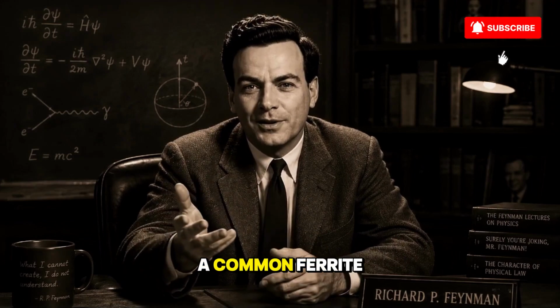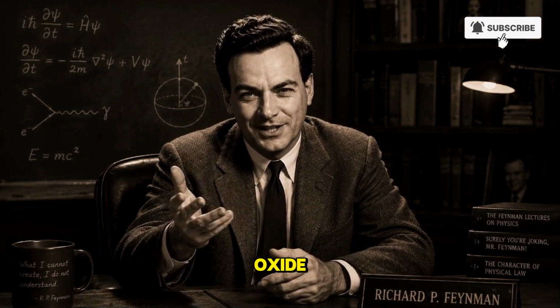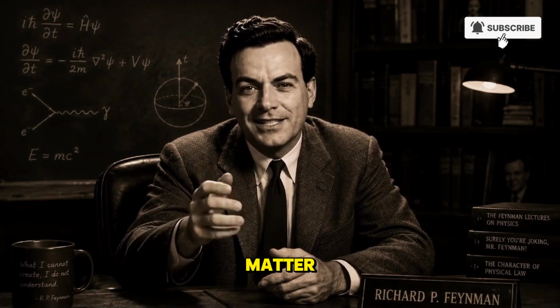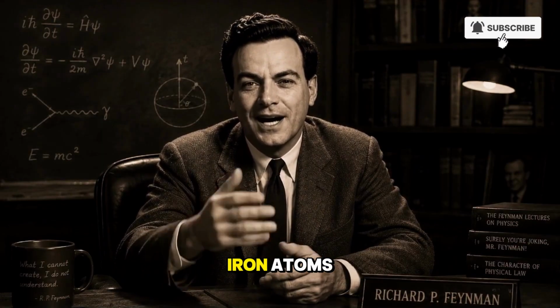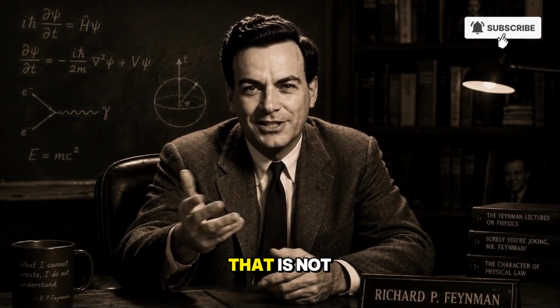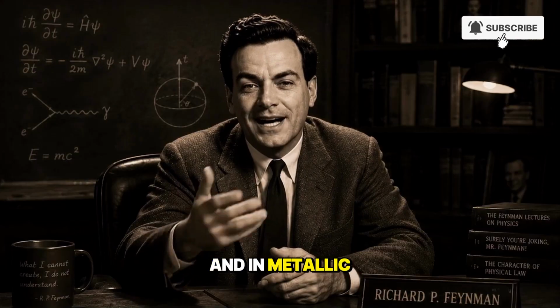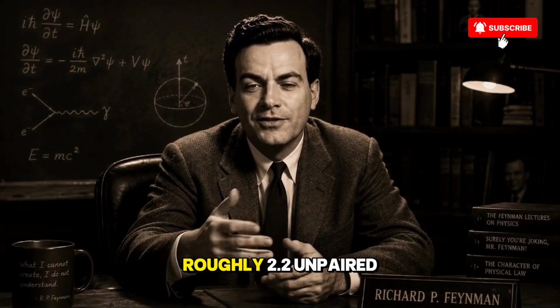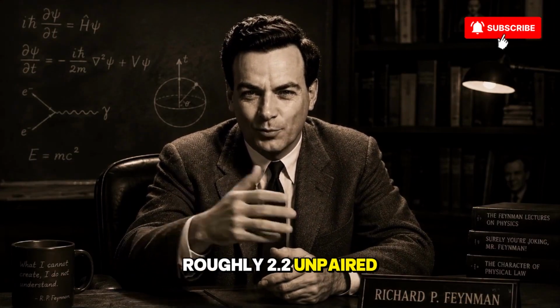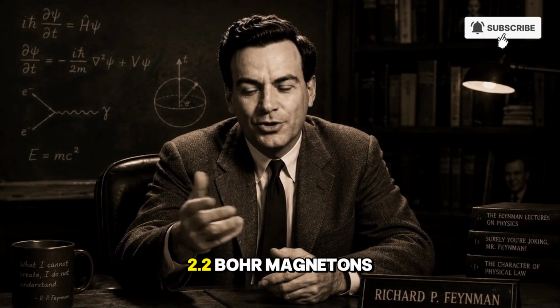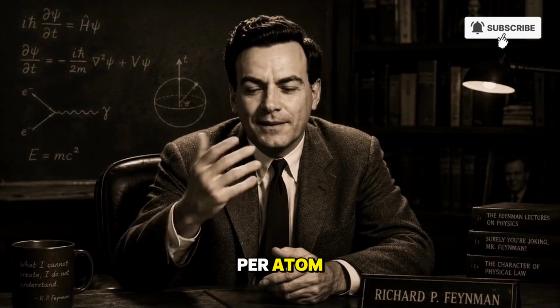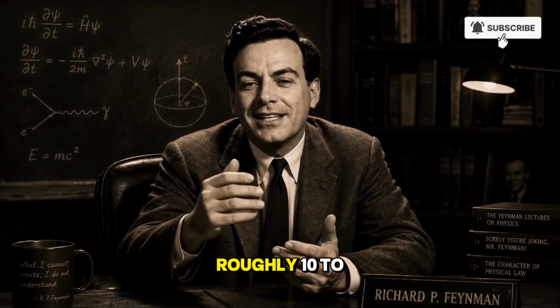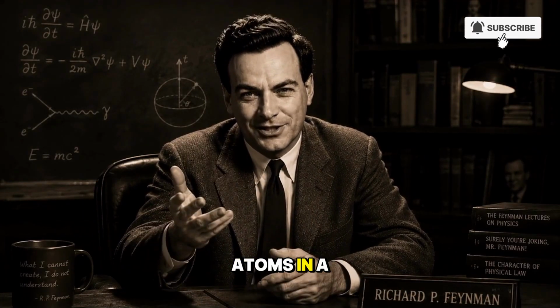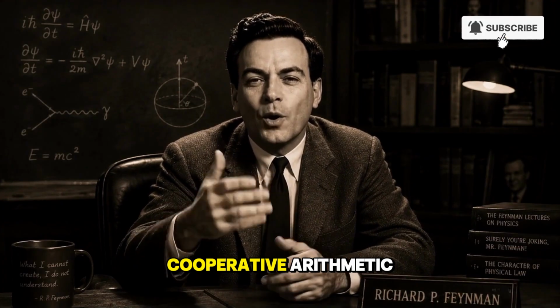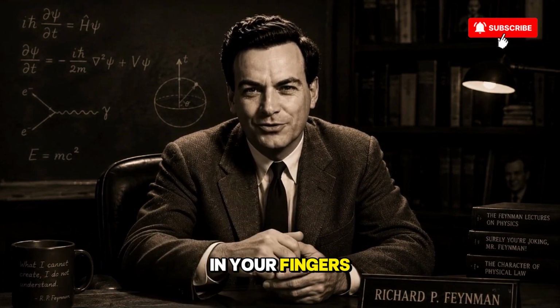The bulk of a common ferrite magnet is iron oxide. The electrons that matter are the 3d electrons of the iron atoms, the outer shell that is not filled, and in metallic iron, each atom contributes roughly 2.2 unpaired Bohr magnetons to the lattice. Hold that figure, 2.2 Bohr magnetons per atom. Multiplied across the roughly 10 to the 22 iron atoms in a gram of metal, that is the cooperative arithmetic doing the work in your fingers.